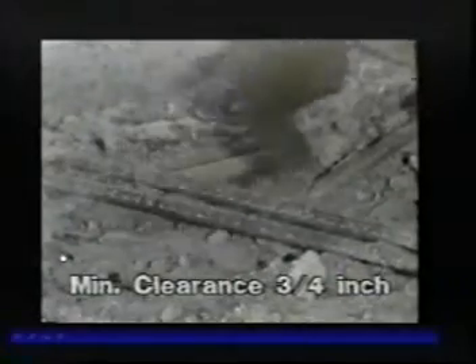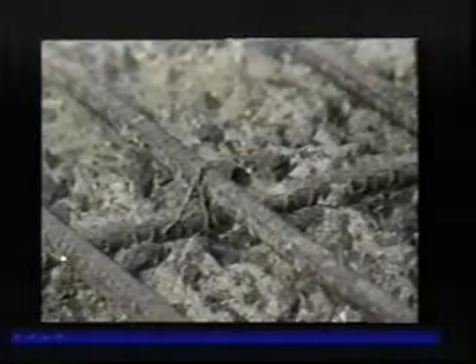You can see here where the hydro demolition was used, the bar was partially exposed, and that particular bar had no corrosion, so it's acceptable to leave that bar without having any removal on the underside. You can see here the 15-pound chipping hammers removing the concrete underneath the reinforcing steel so that we get a good uniform environment with the new material. Vertical and overhead removals are very similar, as you can see here.